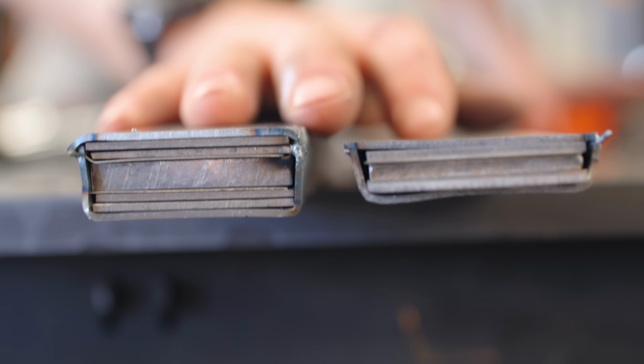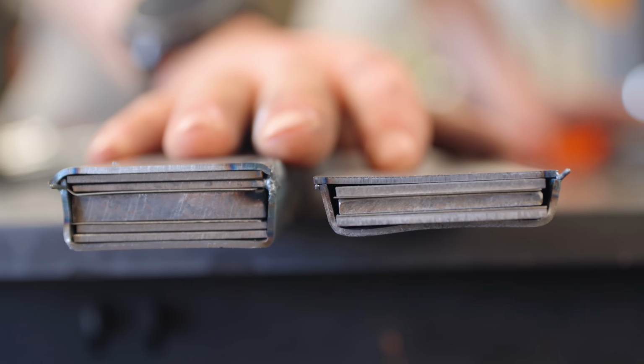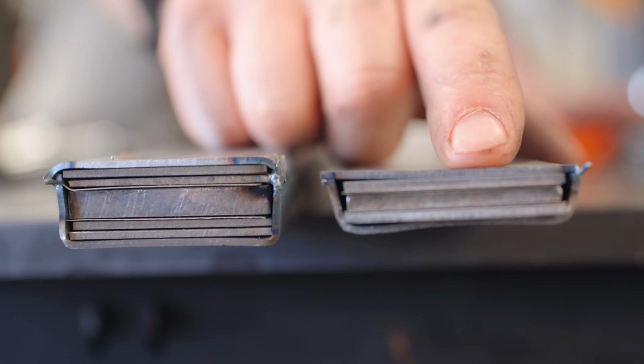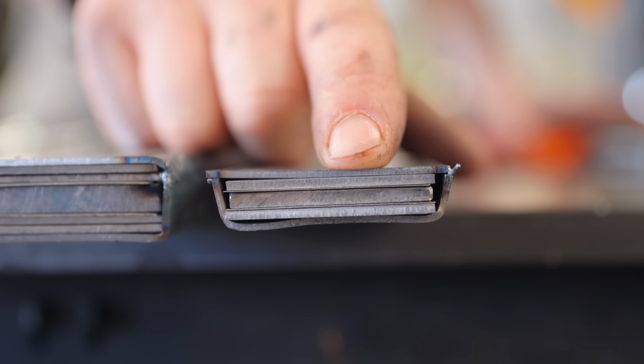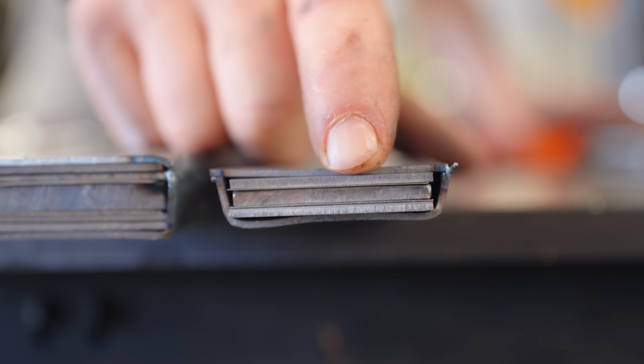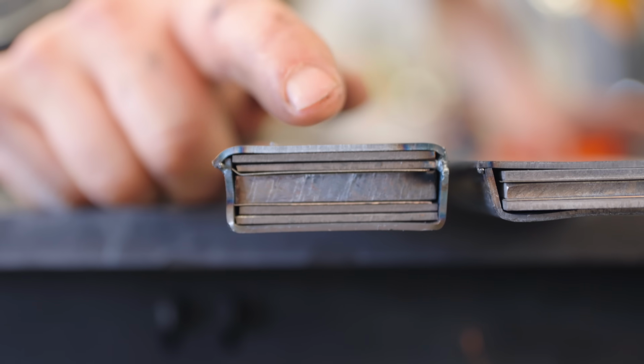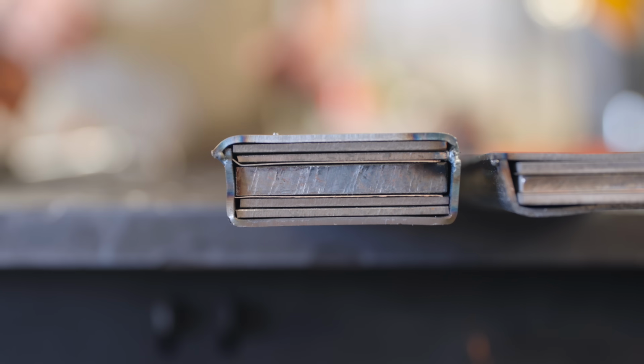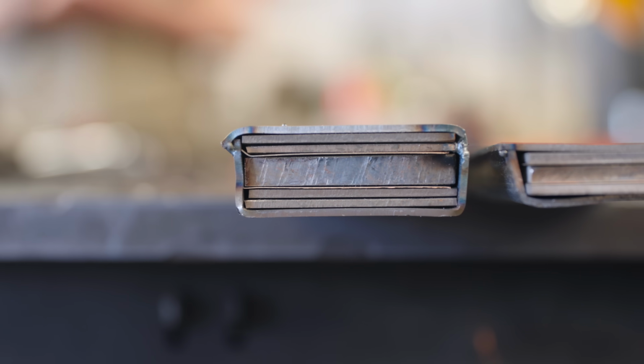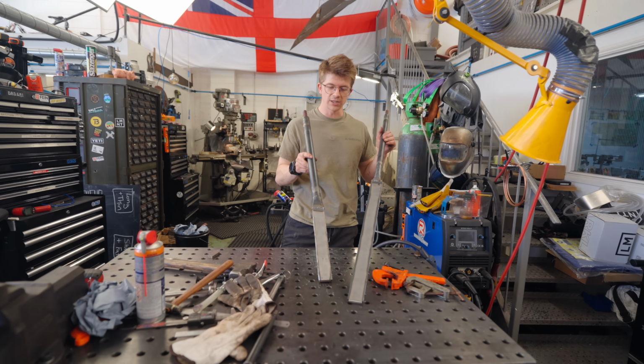There we go, you are now looking down the end of our first 2 experiments. As you will see, we've got on our long and thin billet, titanium, nickel interlayer, steel, nickel interlayer, titanium, and our short and fat has titanium, titanium, nickel interlayer, steel, nickel interlayer, titanium, titanium. Should be obvious now what we are trying to test.